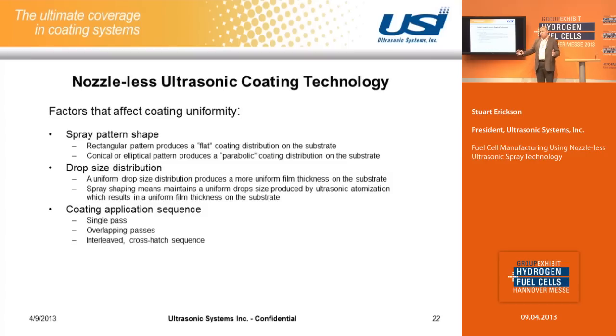So typically when you're dealing with a flat substrate and you want a uniform coating, the more uniform the spray pattern is, the better the coating uniformity is going to be. So a flat rectangular pattern is ideal for applying a uniform coating to a flat substrate. Conical or elliptical patterns produce more coating in the middle, less on the edges, and it's much more difficult to get a uniform coating with those types of patterns. The other thing that matters is the drop size distribution within the pattern. So you have a spray pattern, and if your drops are bigger and smaller in certain areas, you're going to have heavier coatings and lighter coatings. So the key thing is to have a more uniform drop size distribution within the coating pattern itself.